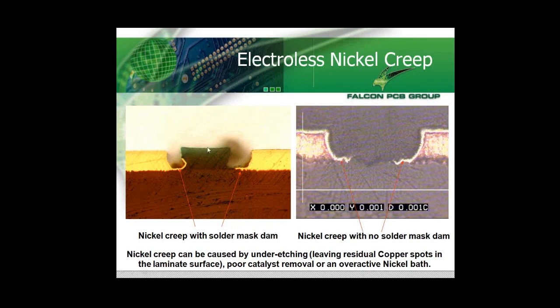What we tend to find is, with the solder mask dams in the centre, and in particular with a little undercut that you can see on both sides, it can be that residual palladium has actually caused the problem for the nickel to metallize. What we do tend to find though with modern lead-free laminates, the copper profile, as you can see a little on the right-hand side photograph here, can be extended from peak to trough, and we're actually seeing quite often peak to troughs of about 8 to 12 microns. If the etching operation on the outer layer is not quite adequate, then you can leave small little tips of the copper dendrites from the copper foil in the actual surface of the laminate. What we also find is that is another process which tends to cause problems with nickel creep.